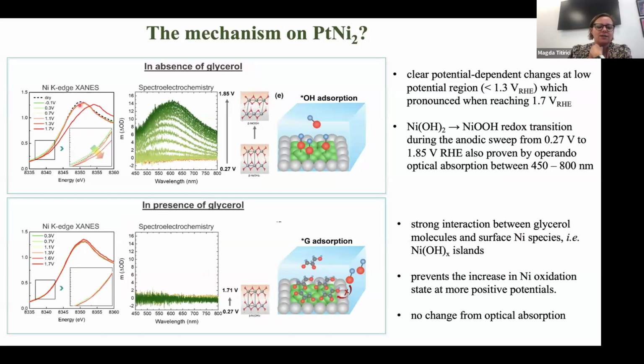And you would see whether this nickel is oxidized or not. And what is interesting is that when you look at the nickel K-edge with XAS, you would see that when you don't have glycerol in your system, you really oxidize your nickel on the surface of the catalyst all the way to nickel oxyhydroxide. So you have a platinum nickel bimetallic. When you do the glycerol oxidation, under those oxidative conditions, you'd form nickel hydroxide anyway, and this goes all the way to nickel oxyhydroxide. So you clearly see an increase in the oxidation state of nickel, and you can nicely see this via spectroelectrochemistry as well.